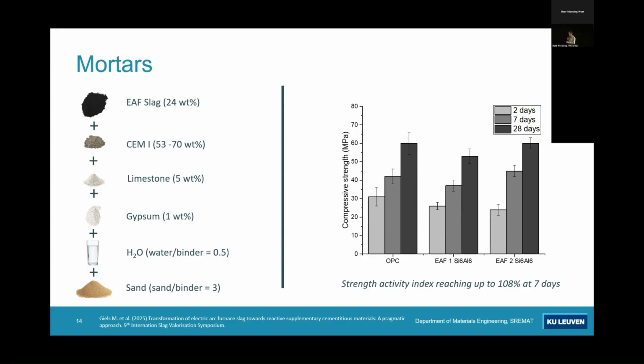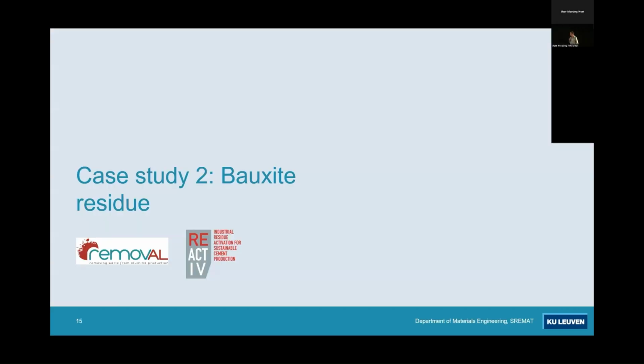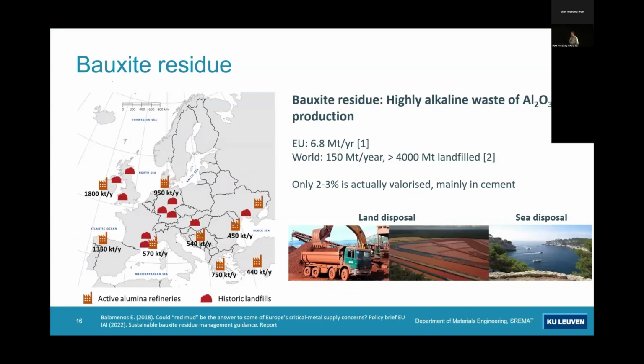Surprisingly, because this material has a very different chemistry to the known SCMs, it's very iron-rich, and these iron-rich SCMs can be, for example, an alternative to blast furnace slag, as we see from performance. So I've done this case study also for other residues, for tailings, for example. One popular, or voluminous, tailing is bauxite residue, not so popular for the people living around these tailings. The world production is quite big, 150 million tons per year, but again, with respect to cement, quite low. But locally, you have quite high volumes.